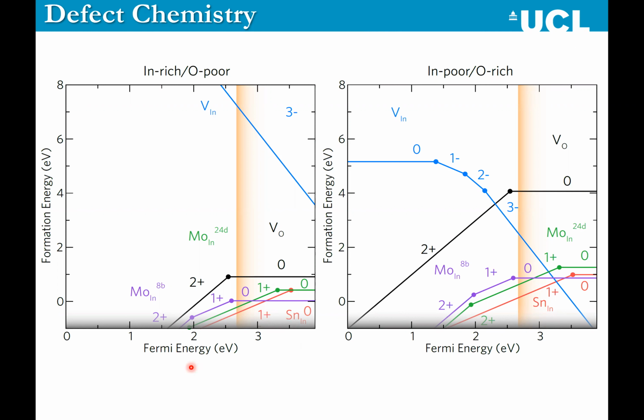So if a defect slopes upwards to the right, it's an N-type defect. If it slopes downward to the right, it's a P-type defect. What this tells you is that under oxygen poor conditions, the formation energy of the N-type defects is much lower than the P-type defects, meaning that the material is N-type. And also under oxygen rich, it is still always N-type until you get to this point here, far above the conduction band minimum, where P-type defects would start to take over. So this material is very easy to make N-type.